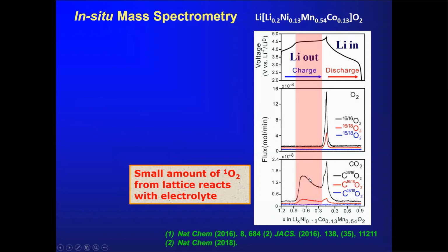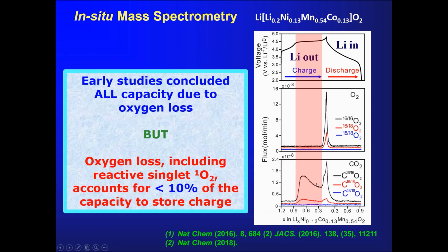And we now understand, and it was very nice work by Hubert Gasteiger in Munich that actually showed that what was happening here was all dioxygen loss, but it was singlet oxygen, a reactive singlet oxygen, and this attacks the organic electrolyte to produce the CO2. And then later you get direct oxygen loss. So the take-home message from all of this is that you get molecular oxygen lost from the surface of the particles, but it's a small proportion of the total capacity. That's the key point. There is oxygen loss, as the original researchers thought, but it is not the whole story.